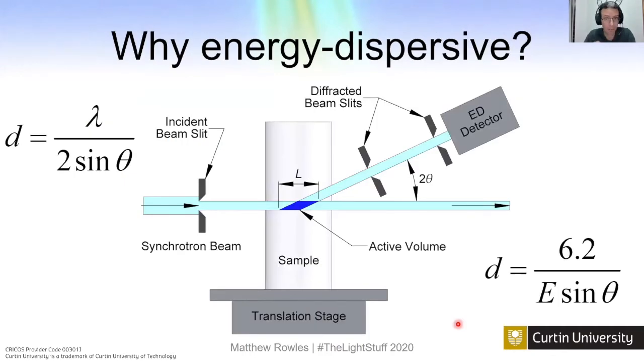We're looking at model anodes using the Magnéli phases — a substoichiometric titanium oxide, TiₙO₂ₙ₋₁, where n is between 4 and 6. We chose energy dispersive diffraction because with conventional angle dispersive diffraction, you use one wavelength and change the angle to sample all d-spacings. For our setup, we needed to isolate a small volume of the anode inside a large reaction vessel. Energy dispersive X-rays use all energies and wavelengths at a single fixed angle. By using pinholes to define both the incoming and outgoing beams, the intersection defines the active scattering volume, which we can position precisely.